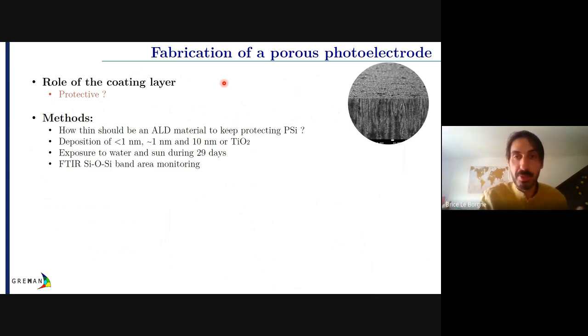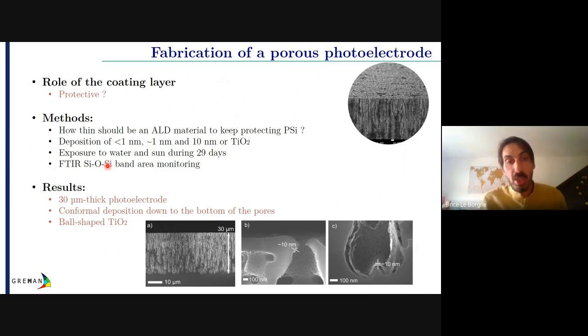So we compare three thicknesses deposited by ALD, and then we exposed our substrate to sunlight and to water during 29 days. Okay, so a month within the water, and of course you would expect the silicon to oxidize. And we've made systematic measurements by infrared spectroscopy, checking the silicon oxide, Si-O-Si bond area to see the evolution of the oxidation. Okay. So first, of course, we checked that we were able to coat the pores, so we made it successfully. And interestingly, you can see that you have this ball-shaped titanium dioxide, which is good for photocatalysis.